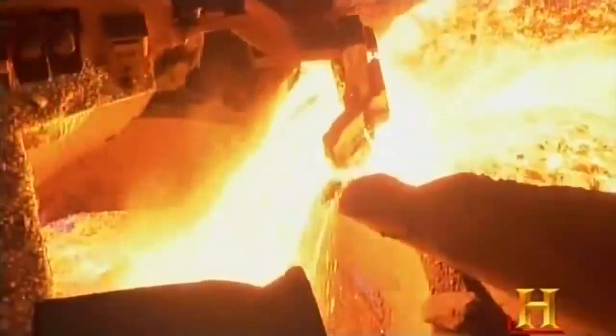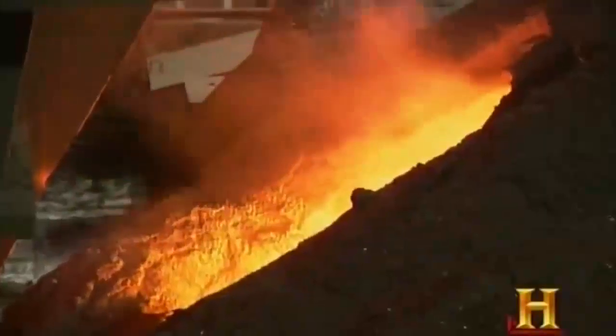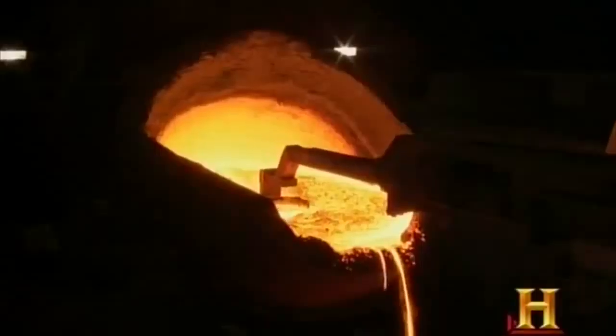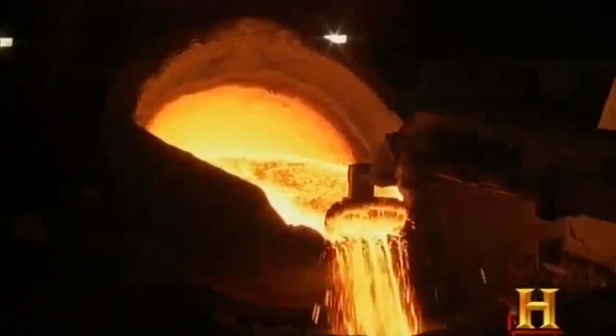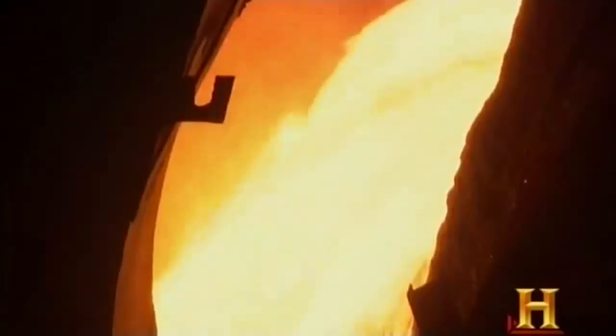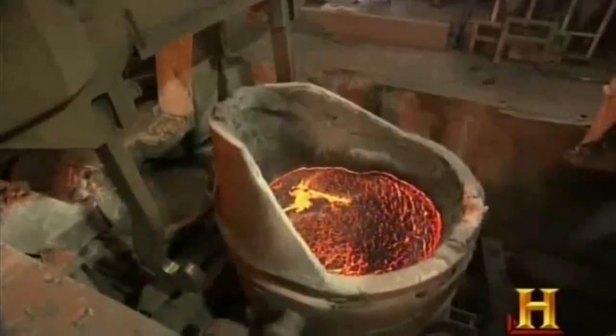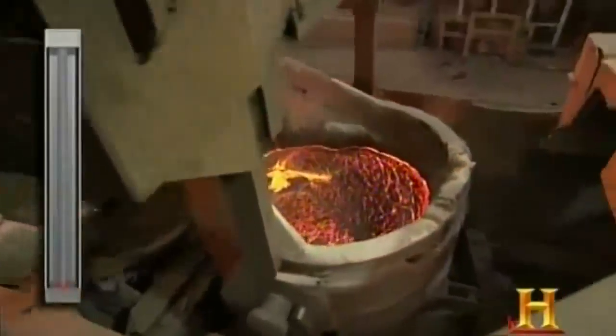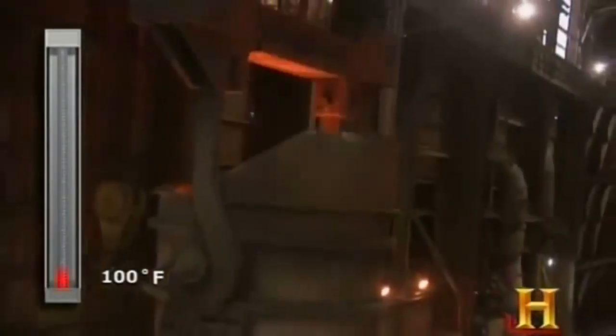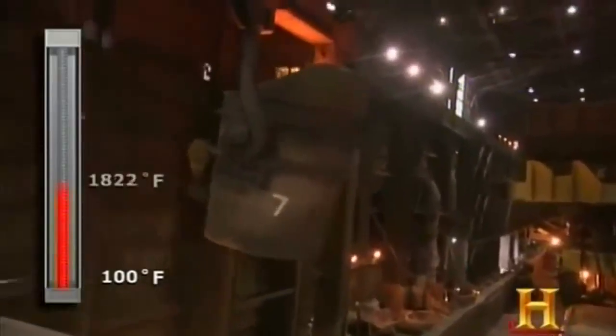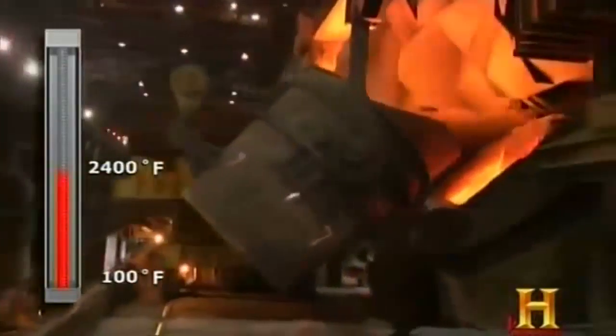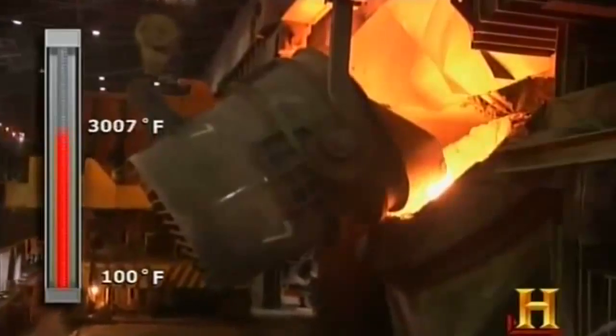But the temperatures the workers face are nothing compared to the temperatures the steel-making equipment must endure. Every transport vessel and processing vessel in the steel shop is refractory lined with different types of brick. We either use a magnesium carbon brick or an alumina brick, depending on the process. To make new steel, the shop combines scrap steel with 2,400-degree molten iron and heats it to 3,100 degrees Fahrenheit in this basic oxygen furnace.